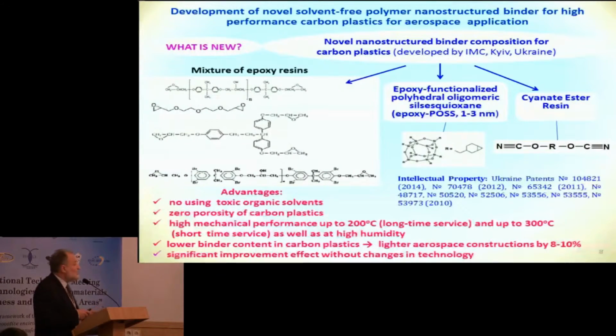So we used as a prototype, for comparison, the conventional industrial epoxy binder EDT-69N, and some analogs EDT-69, EDT-10 for carbon plastics, developed by VIAM, Moscow, Russia, many years ago, and it is still widely used in Russia and in Ukraine as well. This is a mixture of several epoxy resins and a curing agent from the amine class, and a mixture of solvents. And what is the problem of this binder?